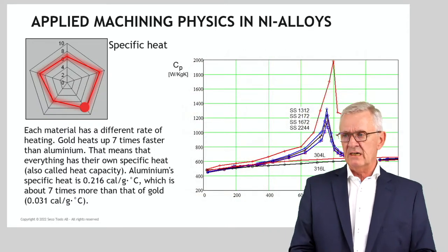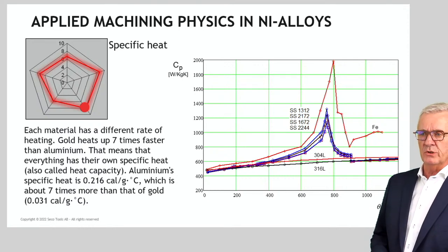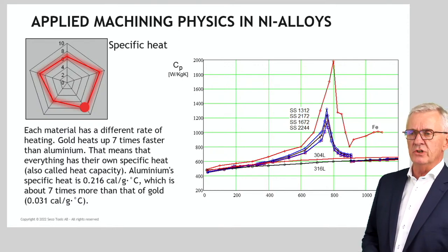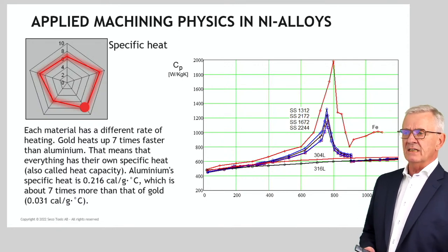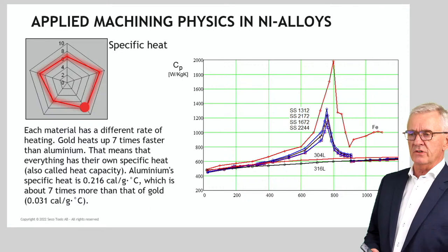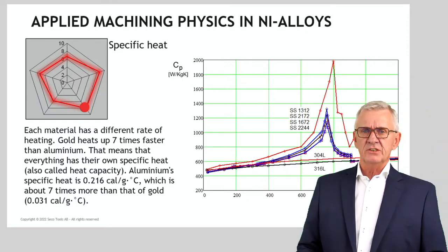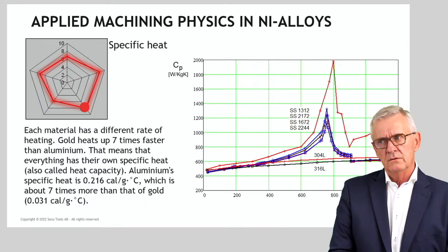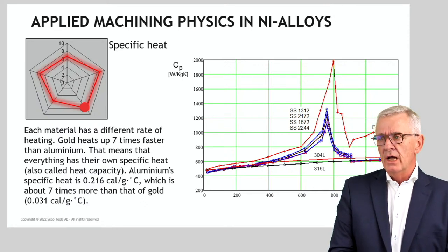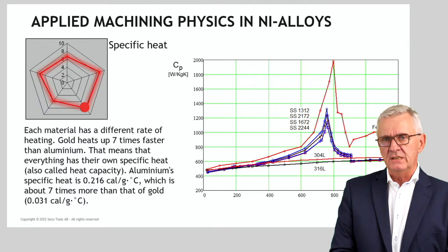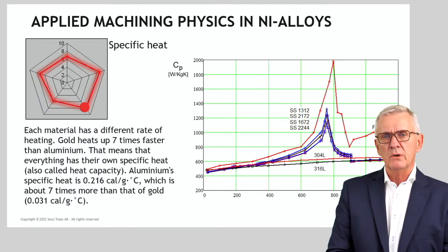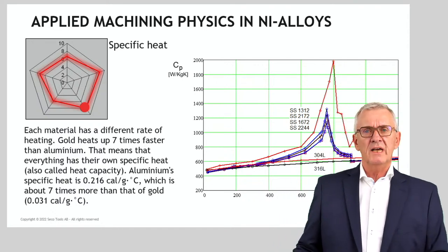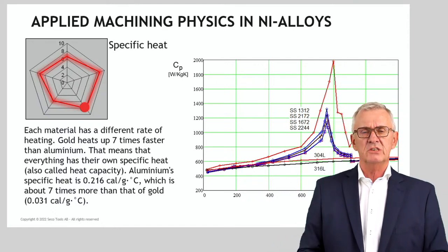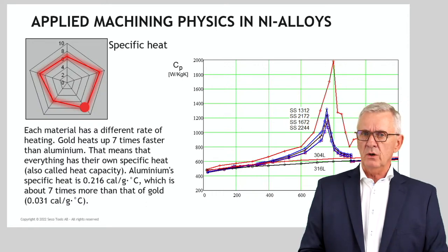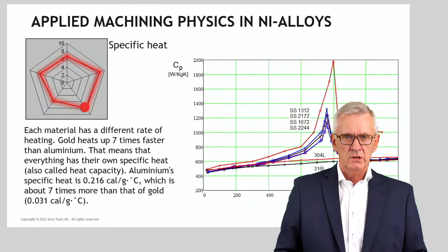In other words, what you see here in the diagram, horizontal is the initial temperature. Vertical is the amount of heat you need to increase the temperature by 1 degree. And the red line, the line peaking there somewhere around 800 degrees, says that traditional steels have kind of a thermal wall somewhere around 800 degrees Celsius. And if you want to increase the temperature even more than 800 degrees Celsius, you need a big amount of heat. Now, in case of machining, where is the heat coming from? Well, from the machining process. And this also explains why you can use low cutting speeds, high cutting speeds in steel materials. The cutting temperature will always somewhere end up around 800 degrees Celsius in the cutting zone.